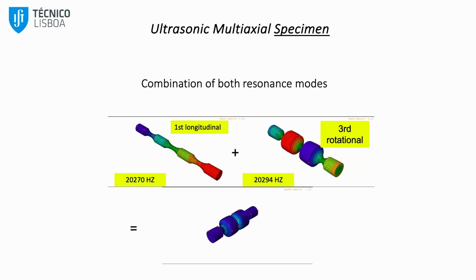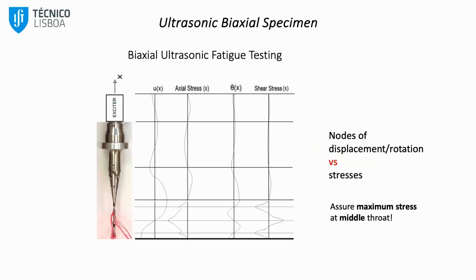The working range of this piezo is from 19.5 to 20.5, so we are in. And for the third rotational resonance mode, we achieved 20,294 Hertz. So we can combine both. And here, just to validate what I'm saying, when we reach the zero displacement, the axial one, we reach the maximum axial stress.